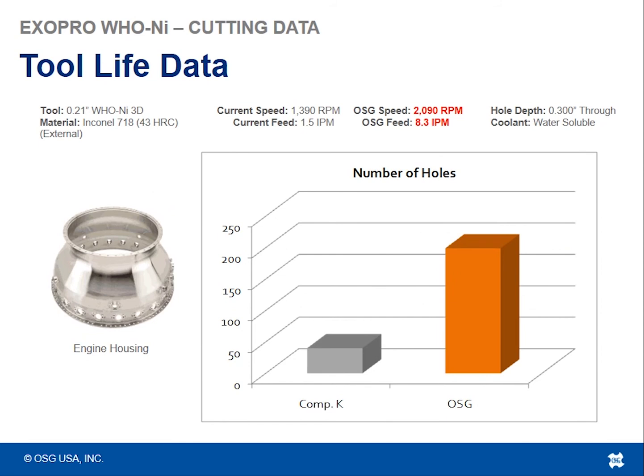This piece of data comes from a customer test from a couple of years back. The WhoNi drill 3xD in Inconel 718, 43 Rockwell. The customer was wanting better tool life from the drill. They were drilling this engine housing component, running at about 1400 RPM and 1.5 inches a minute with the current drill. We came in with the WhoNi 3xD drill, increased the RPM to 2000, and also increased the feed rate to 8.3 inches per minute from 1.5, so a significant productivity increase.